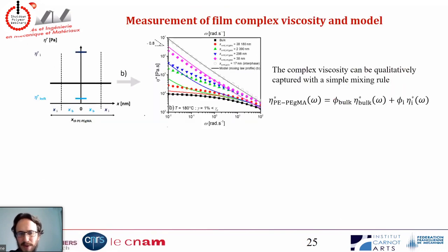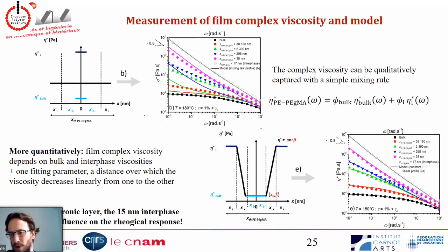And now what we can do with that is we are able to understand the rheological properties of films by only knowing the viscous properties of the interface and of the bulk. It's kind of a mixing rule between the two materials. With only one single parameter, we can fit all the data for all our films really well. And this single parameter is basically the thickness over which the interface and the bulk talk to each other. And what we found is that this thickness is actually quite high. It's on the order of 1 micron. So now we are trying to understand what mechanism can explain this fact that the interface and the bulk see each other over distances that are on the micron scale.